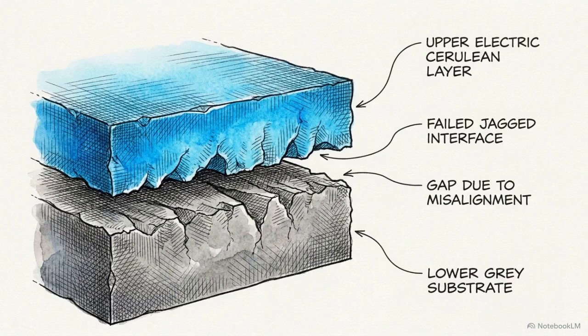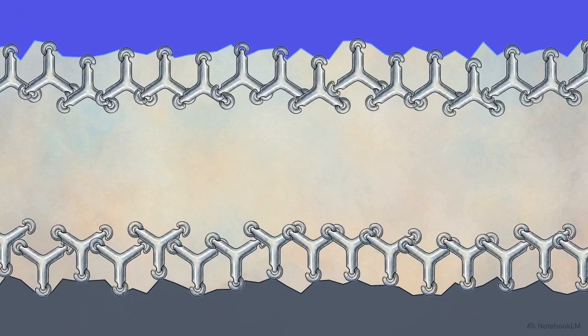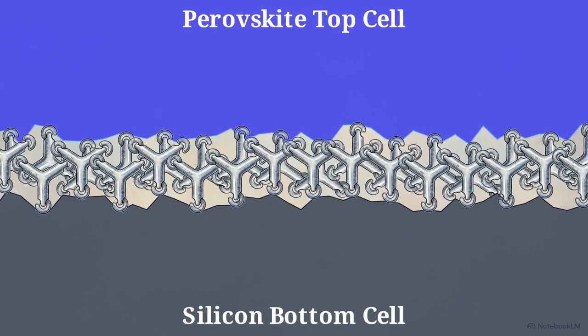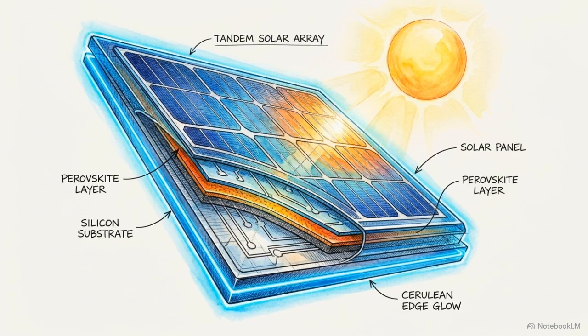The engineering hurdle was securely stacking the materials. Researchers solved this in 2026 using cross-linkable, self-assembled monolayers, specialized polymers that physically bond the layers without impeding the flow of electrons between them. Measured conclusion: tandem technology achieved record efficiency by layering a customized material over silicon to turn an inherent physical weakness into a complementary strength.